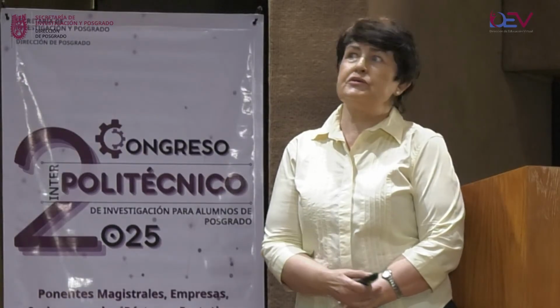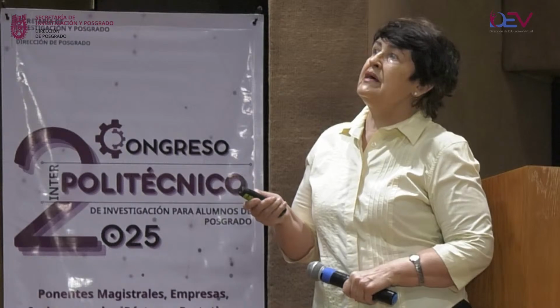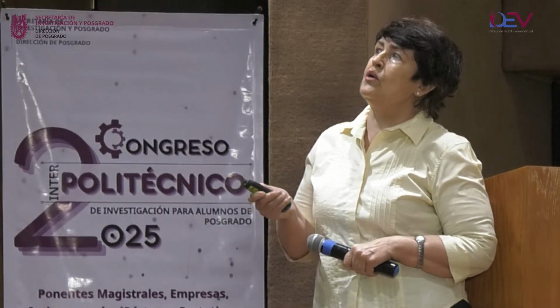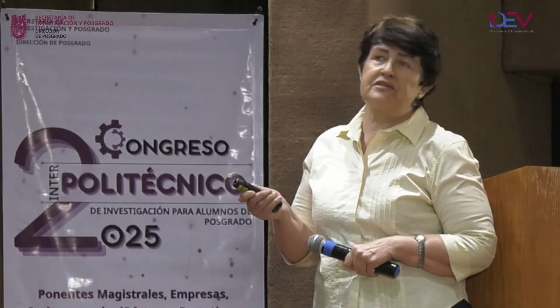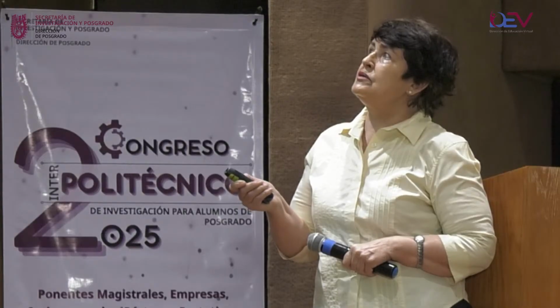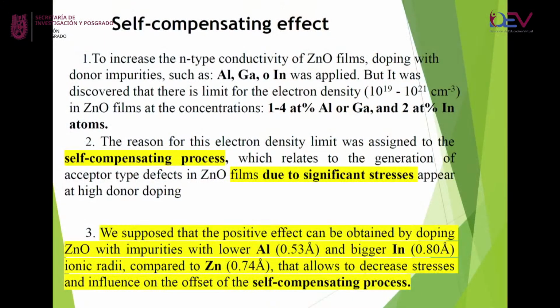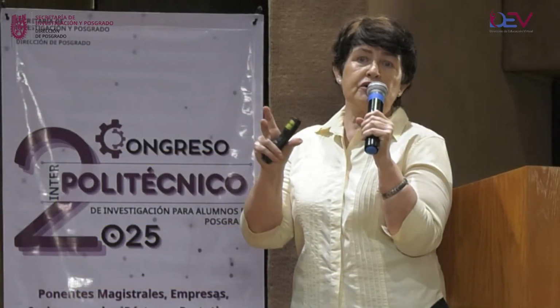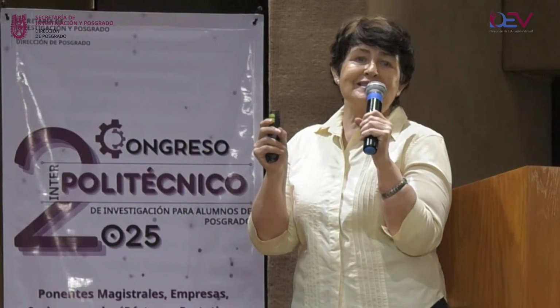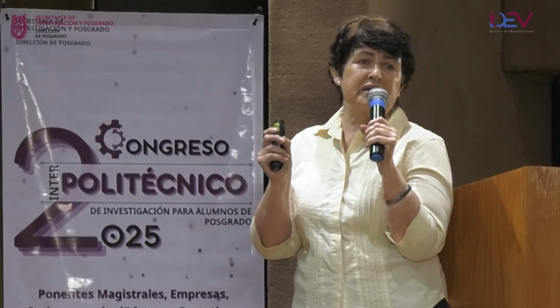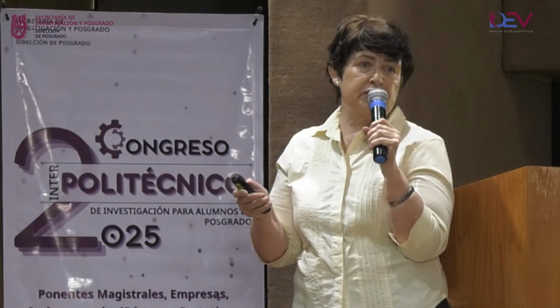We propose to introduce in the material donor impurities with low ionic radii, 0.53, and big ionic radii, 0.8, in comparison with zinc. So we expected that if we take a much smaller ionic radius for the donor impurity and a much higher one for the compensating one, we could receive a crystal lattice parameter just the same as the zinc oxide material has without any donor impurity. Let us see what we received.